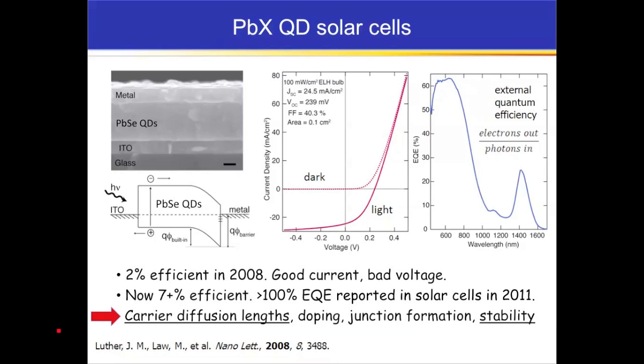And very importantly, as Art probably mentioned yesterday, the NREL group in 2011 demonstrated greater than 100% external quantum efficiency due to multiple exciton generation in a quantum dot solar cell. So this effect is real and can actually be used in real devices. At this point, it's a little bit too weak to really make a big difference in terms of the efficiency, but some breakthroughs would change that. But to go from 7.5% to something like 15 to 20% efficiency is what we would really like to see to be a practical technology of relevance.